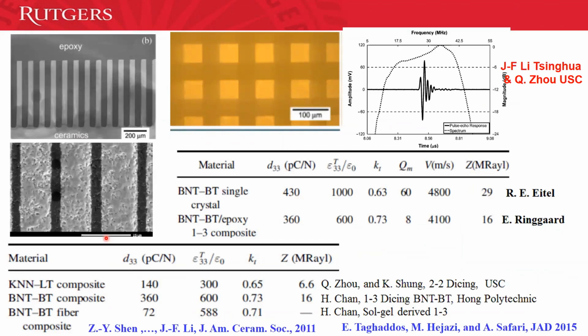Those are low frequency. In terms of high frequency, there is a lot of PZT and recently some other ceramic polymer composites. I am noting a few different contributions. This is from Jinfeng Li and Qiufa Zhou, Jinfeng Li from Tsinghua, Qiufa from USC. They made KNN-based material by dicing and making composites. This is about 32 megahertz center frequency, with very nice bandwidth, about 70% at minus 6 dB. Then some other scientists around the world made these composites, KNN-LT ceramic polymer composites, and BNT single crystals and BNT fiber composites, which give really encouraging results overall for the development of ceramic polymer composites.